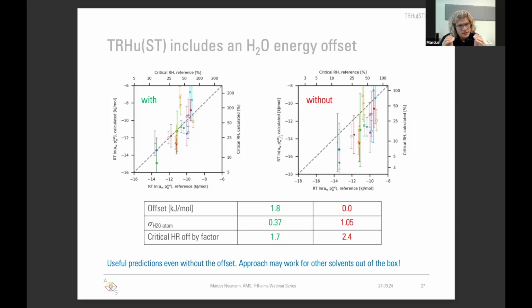So we first look at the green number. This green number is related to relative humidity prediction with the offset. And so over all those relative humidity predictions, we get the prediction of the phase transition relative humidity right to within a factor of 1.7. So this is not 1.7% of relative humidity, this is a factor of 1.7. That means that if we predict a phase transition at 10% relative humidity, it may be, so the 1 sigma interval is from somewhere 7 to 17%.